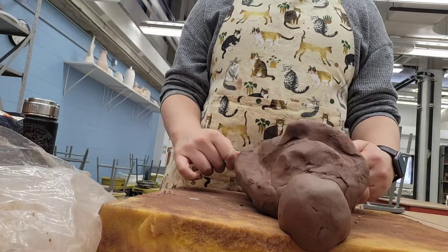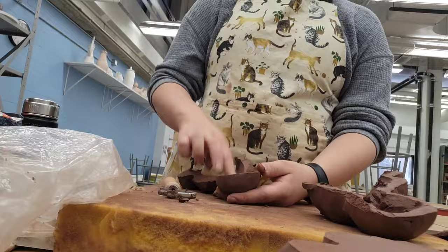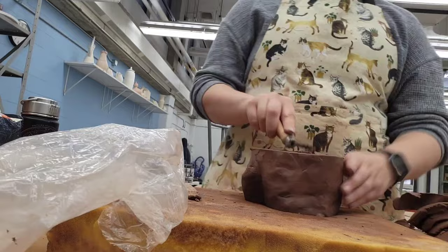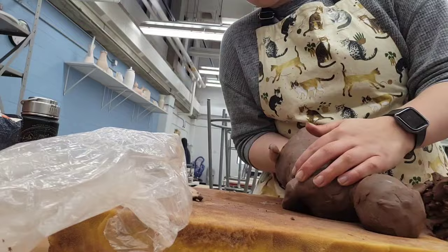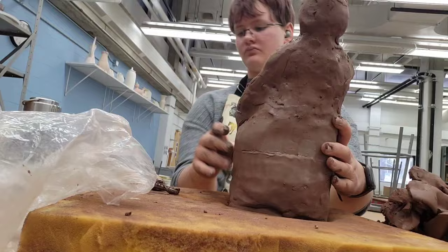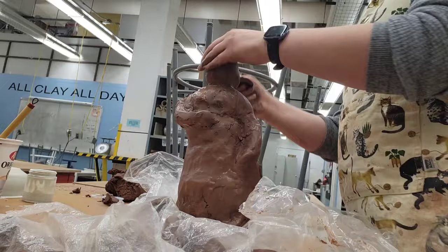And here's probably the most fun part of sculpting the statue — cutting it apart and digging out all the insides. It's such a fun process. I don't usually like sculpting, but this is a really fun thing to do. Then just sticking it back together, trying my best to make sure it doesn't crack — it might crack along those lines, but what can you do? The really nice thing about this process is that because of the air pressure inside, once you get it all put together, you still have that really nice solid form — the air pressure keeps it nice for sculpting — but it's also much lighter. I was trying to lift this before it was hollowed out and I almost dropped it. Then when the process is done, you just poke a couple of holes into it to let the air out, so that you don't create a bomb in the kiln, basically. Then I picked it up, wetted it down, and it started cracking, and I had to smooth it out. I really hope that doesn't make it crack more later on.